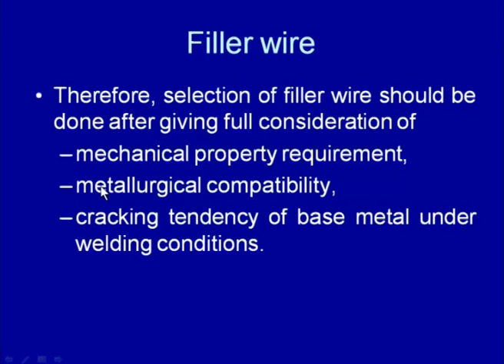We would also like to see whether the filler material is metallurgically compatible or not. The use of metallurgically incompatible materials can lead to embrittlement or cracking during the welding or just after the welding, and the purpose may be lost as far as the development of a weld joint for taking the service load is concerned. Further, we need to see how the filler material can help in controlling the cracking tendency of the weld metal.